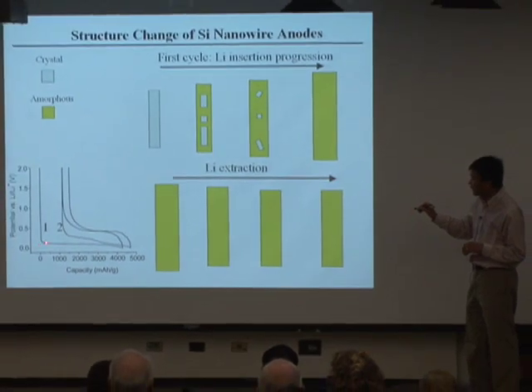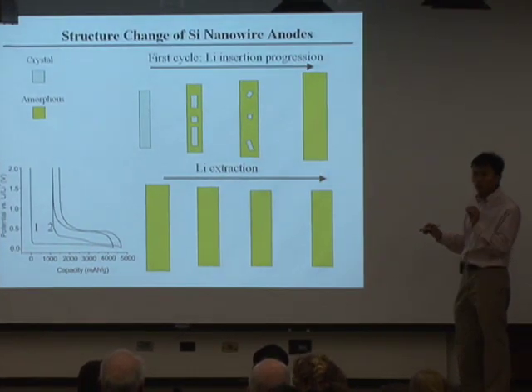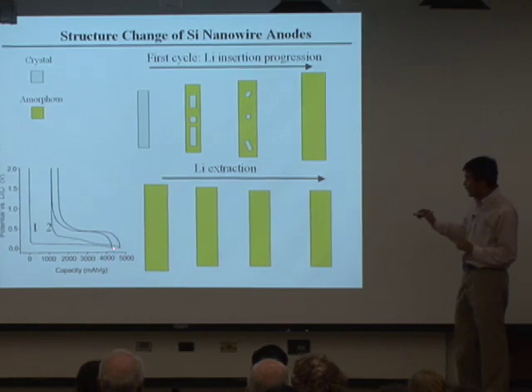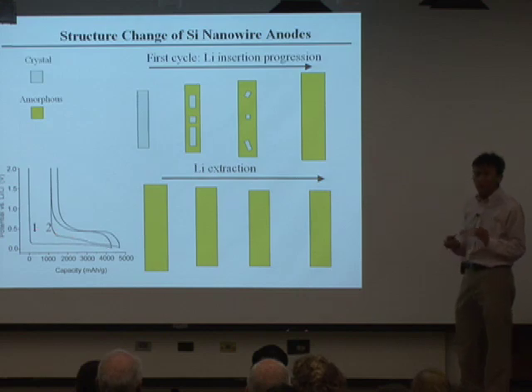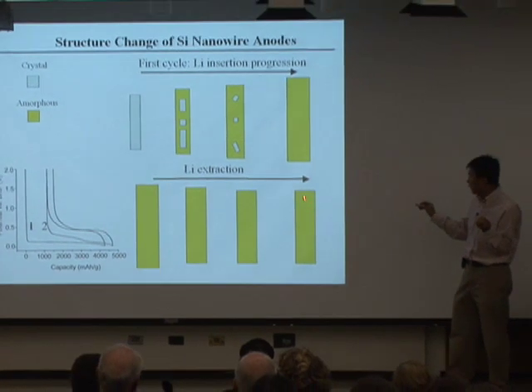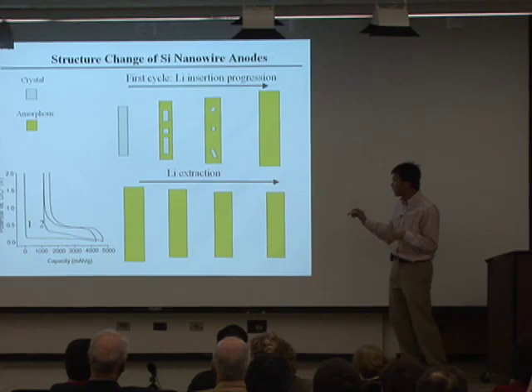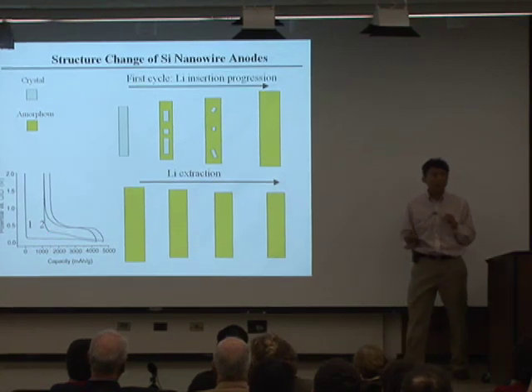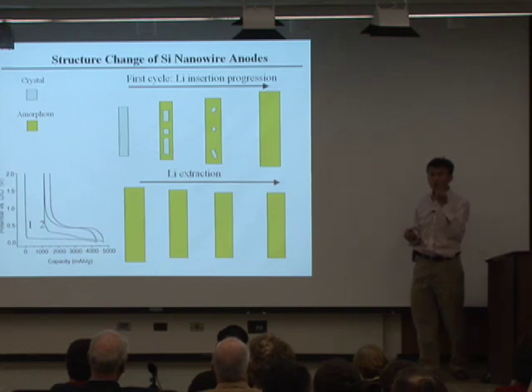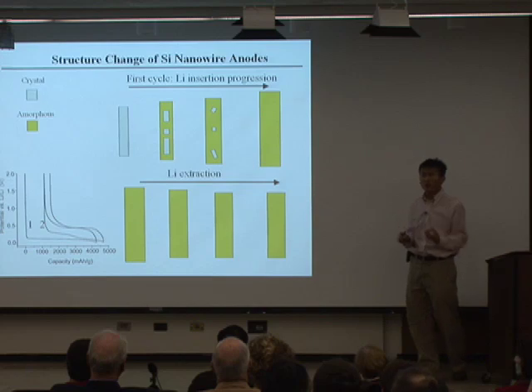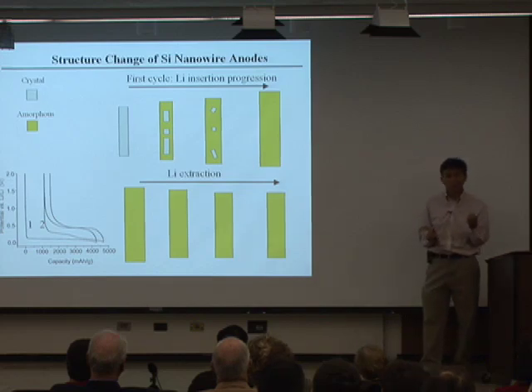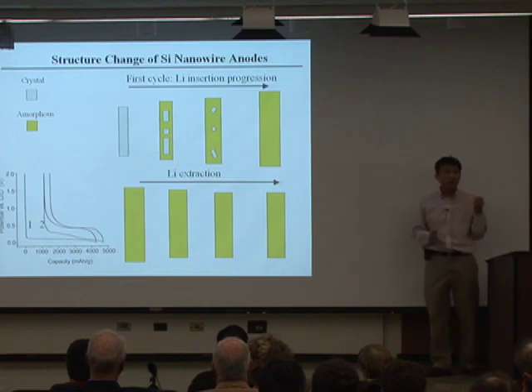When you charge up your batteries during the first charge cycle, you need to go down to low potential to charge lithium into silicon. When you get to right here, they all become amorphous. Now you take lithium out. You come to the second cycle, you charge it again, and you start with amorphous silicon nanowire from here, and start to put lithium in. Now you see the potential value you need to charge lithium into amorphous silicon is different from the potential you need to charge lithium into crystalline silicon. So it is different between amorphous and crystalline. Well, that really activated our minds.